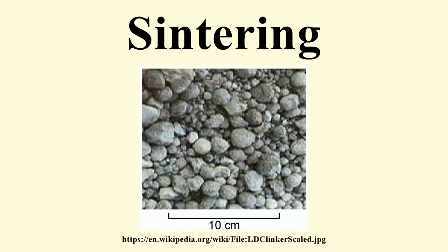All the characteristic temperatures associated with phase transformation, glass transitions, and melting points occurring during a sinterization cycle of a particular ceramics formulation can be easily obtained by observing the expansion temperature curves during optical dilatometer thermal analysis. In fact, sinterization is associated with a remarkable shrinkage of the material because glass phases flow once their transition temperature is reached, and start consolidating the powdery structure and considerably reducing the porosity of the material.